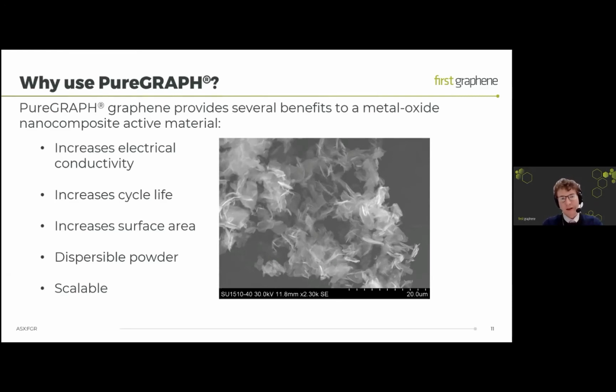We also can increase the cycle life by having those oxides directly deposited on the surface. Metal oxides in a supercapacitor would traditionally sort of dissolve into the electrolyte, and they would also crack as they change oxidation state. As you oxidize and reduce the metal ions, they form different structures, and therefore you can get breakdown of the metal oxides. By having them in contact with the graphene, we can reduce that. We can reduce the effect of the solvation and the breakdown of these metal oxides by having that contact there.